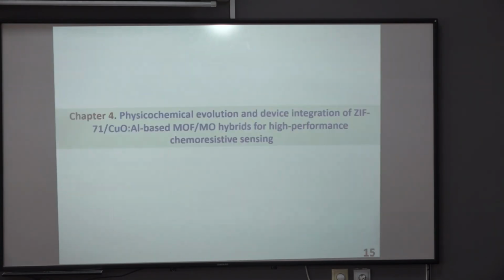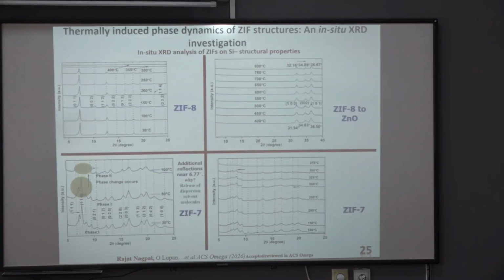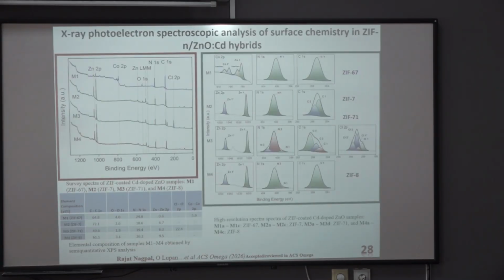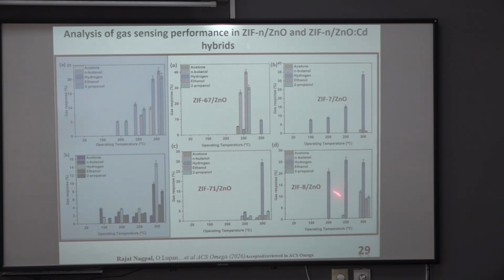If we go to the zinc oxide sample, here we can see, in this case it is ZIF8, high sensing response can be observed, but at 200 degrees Celsius we cannot see any sensing response for other VOCs. Even at 250 degrees Celsius, negligible sensing response. So here we can see, even at 200 and 250 degrees Celsius, in the case of ZIF8 copper oxide hybrids, we saw appreciable sensing response for VOCs, but not in this case. But definitely for hydrogen, in both cases, it shows high sensing response.